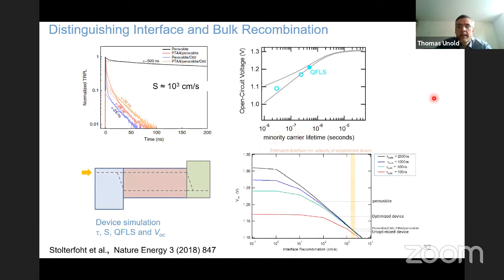And maybe the last thing I want to mention, because this was also a discussion we had with the reviewers of that publication, is what does it mean if you look at the VOC? We did some simulations here, and this says VOC, but it should be the quasi-Fermi level splitting. Here is shown the interface recombination. There are different assumed interface recombinations, and these curves are different assumed bulk recombination lifetimes. This one is a very large one, 2.5 microsecond. This is a very small one, 100 nanosecond. And now we can look at the VOC of the unoptimized device. It was here.